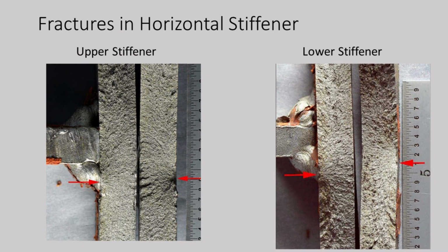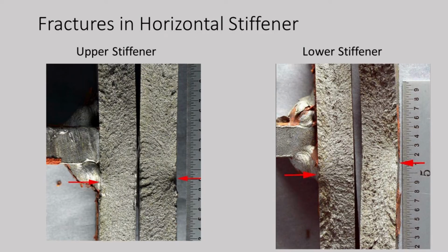Kentucky likes horizontal stiffeners on fascia girders for aesthetics, if nothing else. We got a crack here that didn't quite make it to the upper flange. Then we have a crack here that interplayed with the top crack, but it also ran down and it had jumped or was jumping into the lower flange at the time of the cabinet's investigation. They took that picture. So they asked us to inspect this and see what we could find.